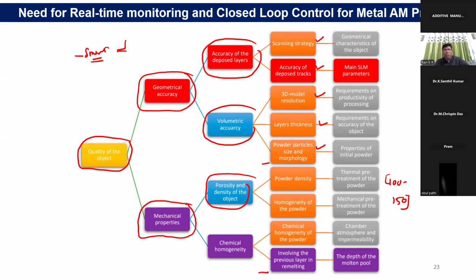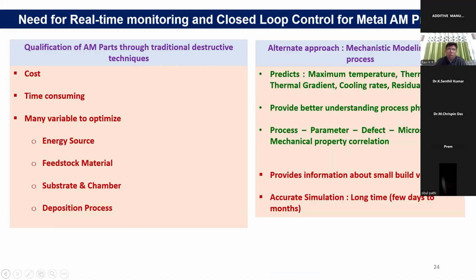Okay, so if you really want to have the minimum defects and chemical homogeneity, we need to have smart metal AM process. But all these parameter variations, usually people do with the conventional traditional method by making the parts and then doing the microstructure and mechanical property. Then you vary the parameters and repeat this process. By doing this, even for any new material, you need a time of 1.5 to 2 years to identify the optimum process parameters.